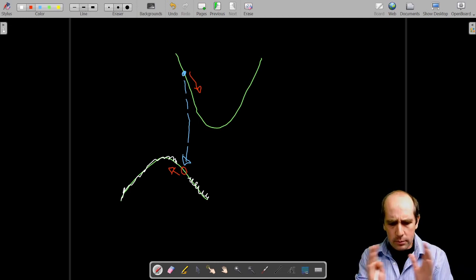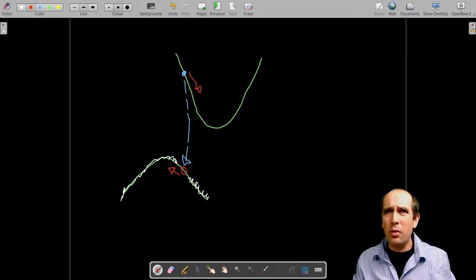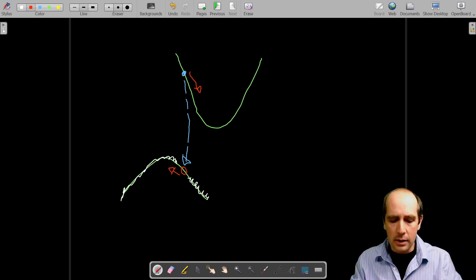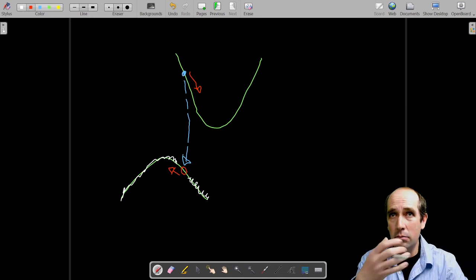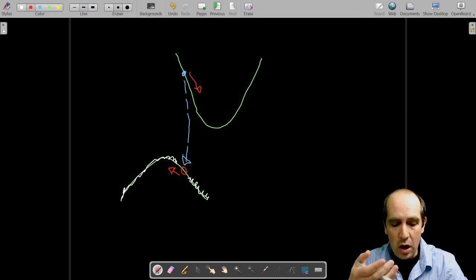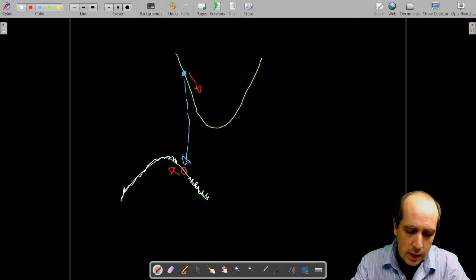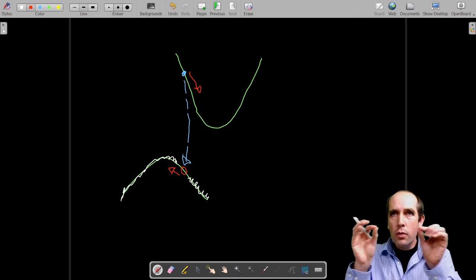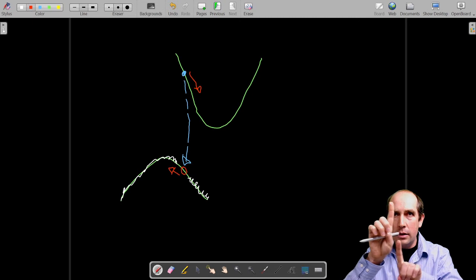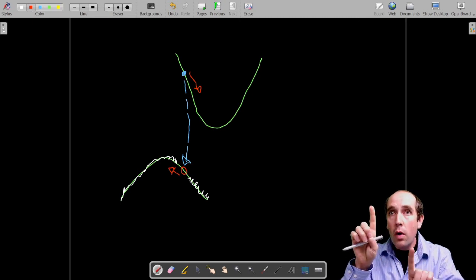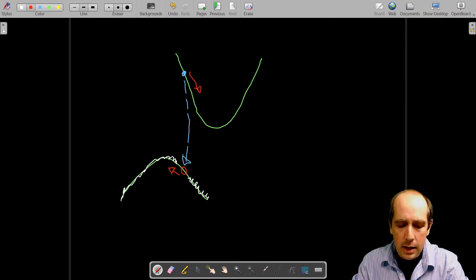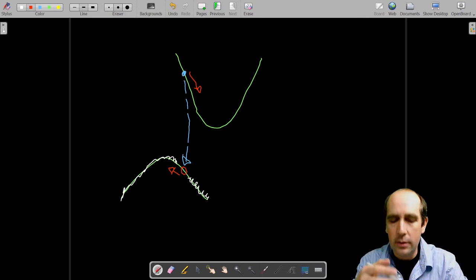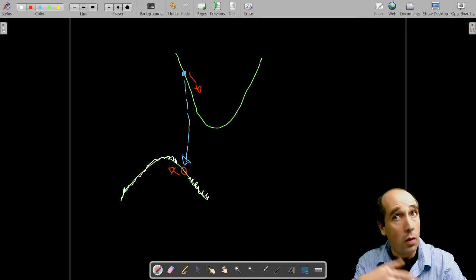And this is what these red arrows mean. So the two possibilities are available, and the question is, which one is more likely? I will not go into the details of why, but the thermal transitions are far more likely. As soon as one of the two starts moving away, so that the two K vectors are no longer aligned, the optically mediated photon transition is no longer available.